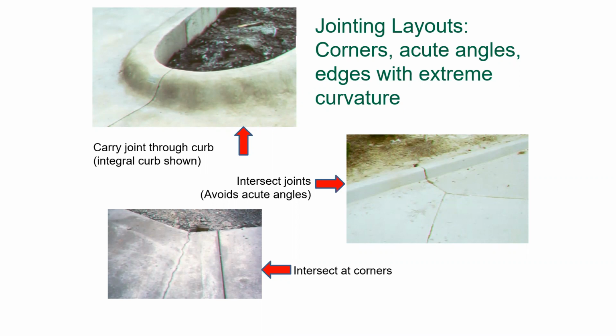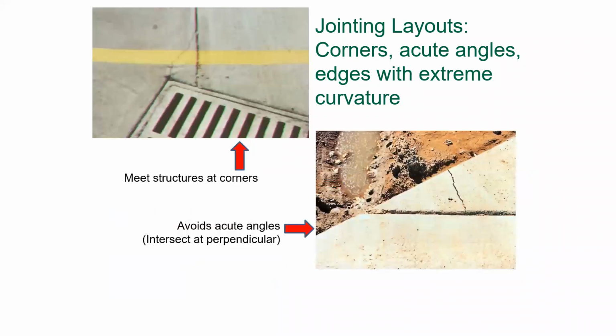Any type of intersecting joint, in the picture down at the bottom, you really want to cut that joint at the edge of the slab to try and get that joint over by that angle coming into the slab. Where you've got an inlet coming in, with corners coming off the inlet, that crack is going to want to form. So you want to have the saw cut joint before you get to the inlet. That's really what you want to consider. You'll also see the concrete cracking where it wanted to, instead of where it was placed, with that acute angle.